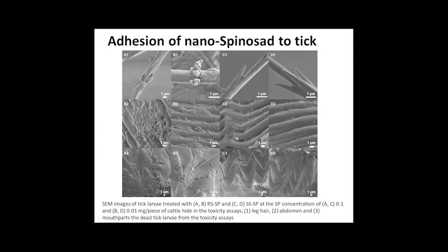In contrast, smooth spinosad only shows several nanoparticles adhering on these tick body parts at a spinosad concentration of 0.1, and almost disappeared at the concentration of 0.01. This SEM observation further demonstrates the advantage of the rough surface nanotopography in introducing a superior adhesive property to the tick body and leading to improved pesticide-pest contact for high toxicity.